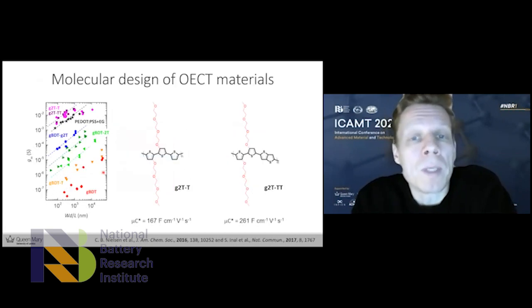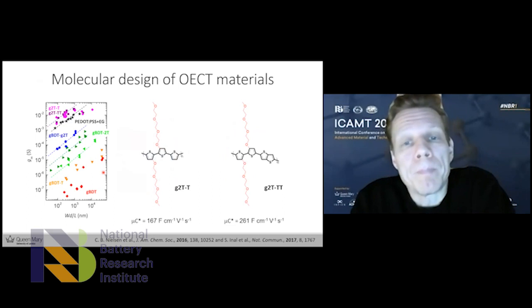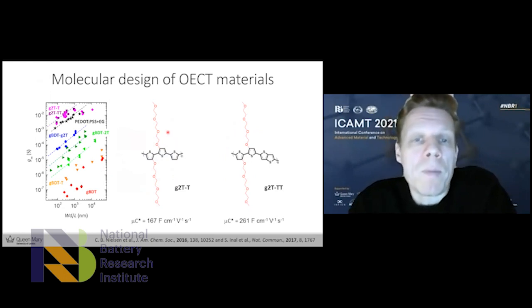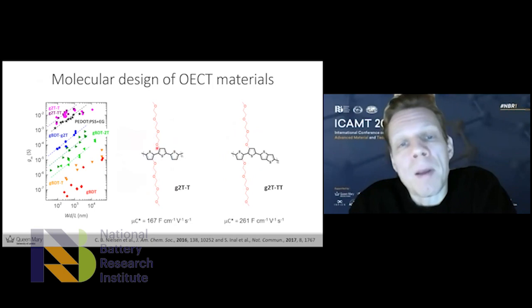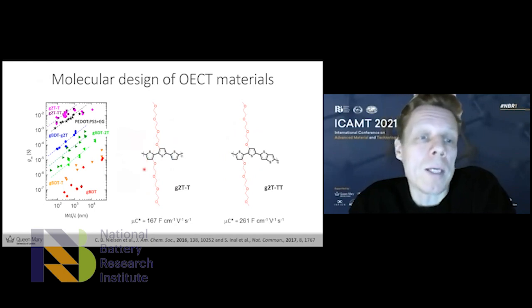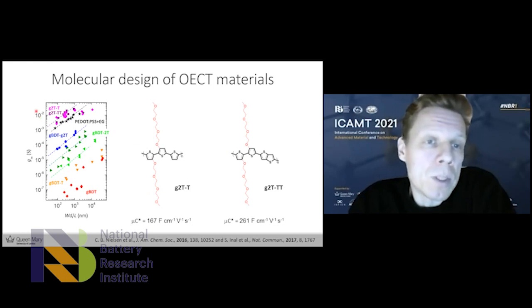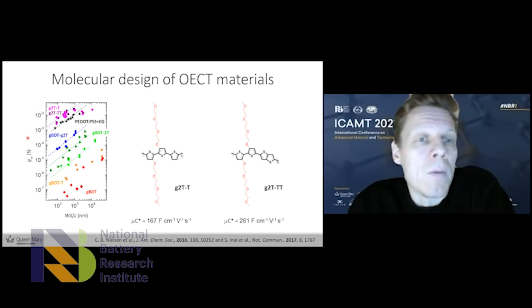So that turns out to be a quite nice materials design criterion for making these mixed conduction organic semiconductors. And we made several families of these types of materials, and we see that they work quite nicely. I won't go too much into details about this plot here, but on the y-axis, we have the transconductance that I talked about before as a figure of merit for the sensing capabilities.